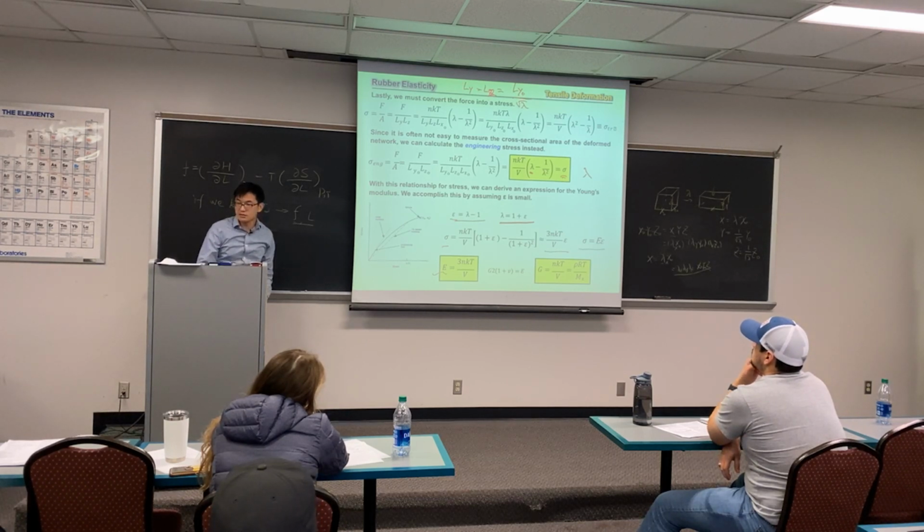Stress is related to the strain by Young's modulus, so you can get the Young's modulus using the same theory. Young's modulus, as you can tell, is 3 times nkT divided by volume. You can also predict